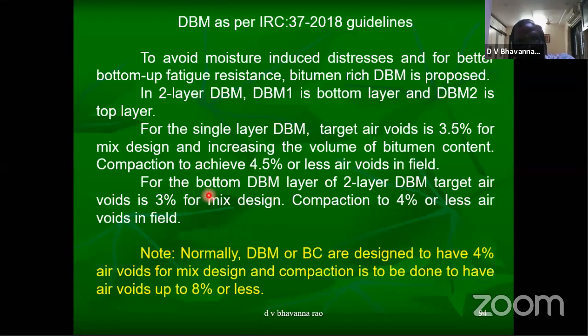If you are going for two layers of DBM, for the bottom DBM layer of two-layer DBM, target air voids is 3% for mix design. Compaction to achieve 4% or less air voids in the field. We have to change the design of DBM during execution, and it may lead to some variation in the bitumen content also. But to reduce fatigue cracking, bottom-up cracking, which is common in the bottom layers of DBM on high traffic roads, IRC 37 has recommended this.